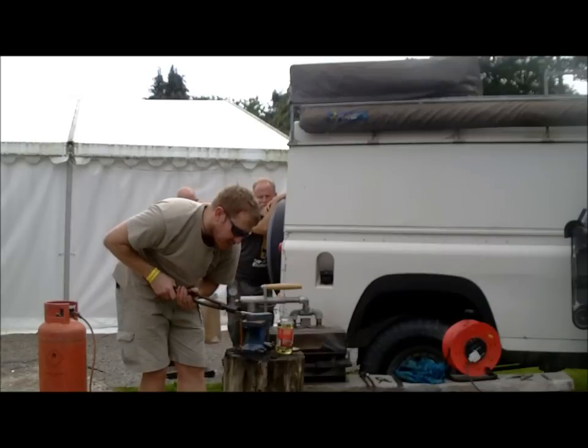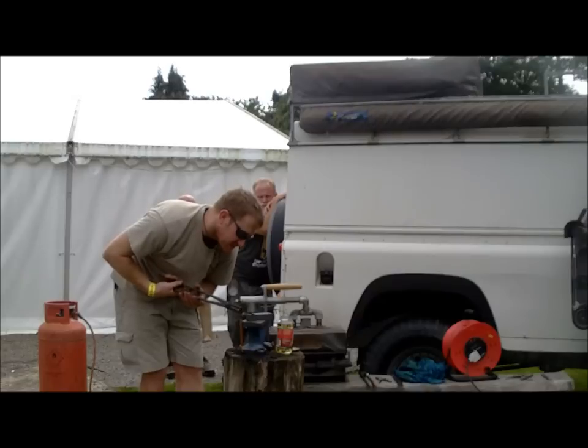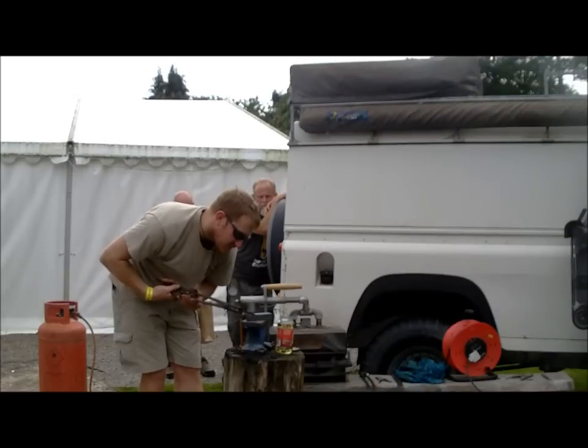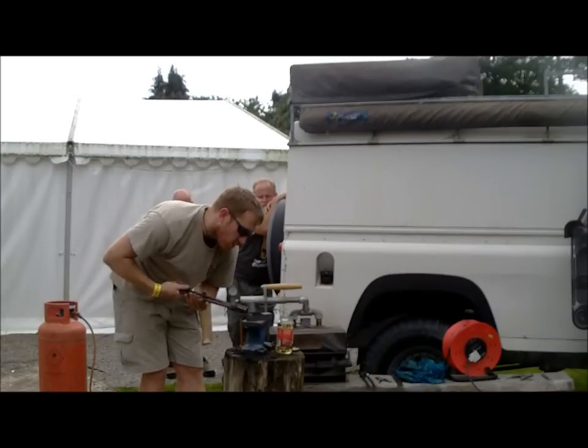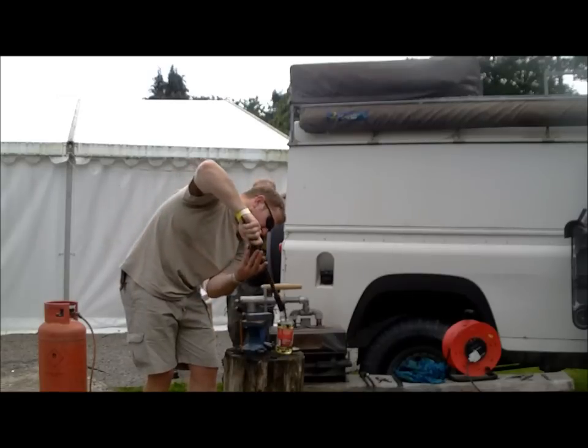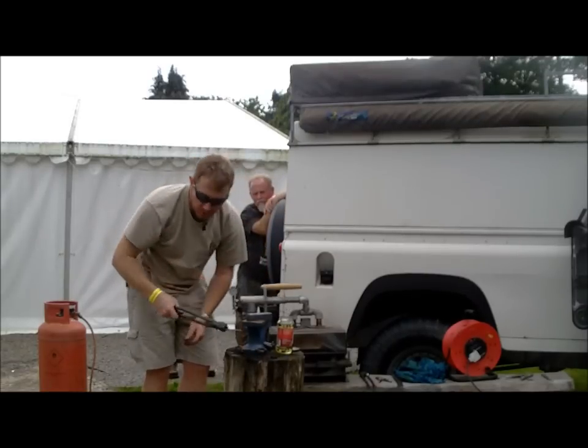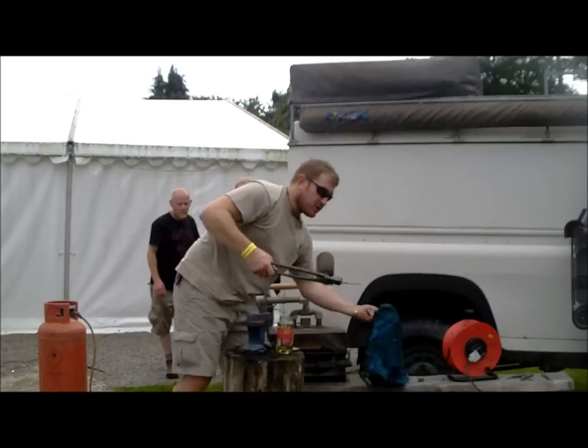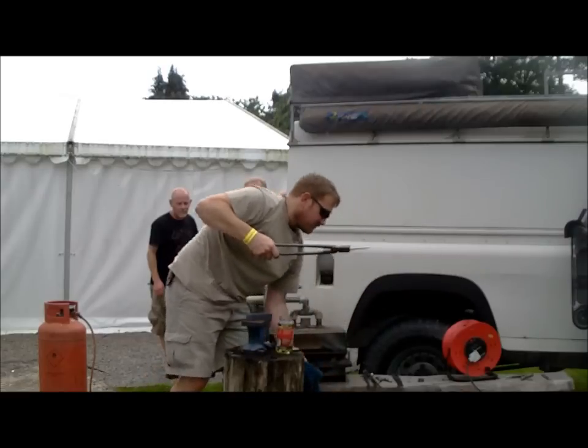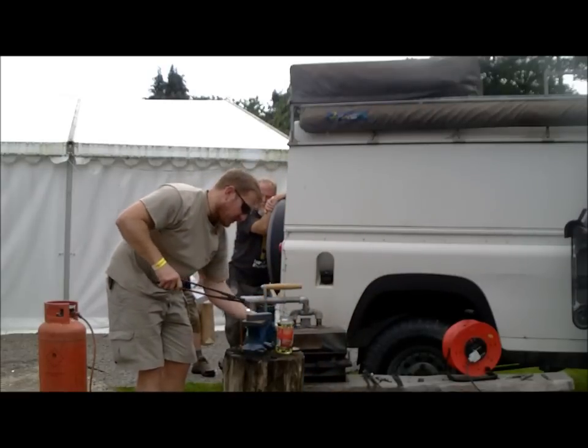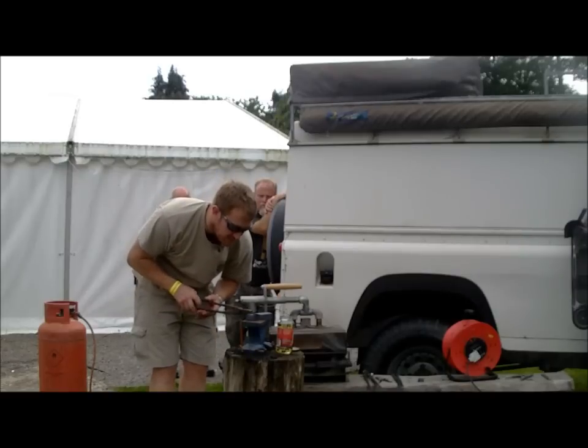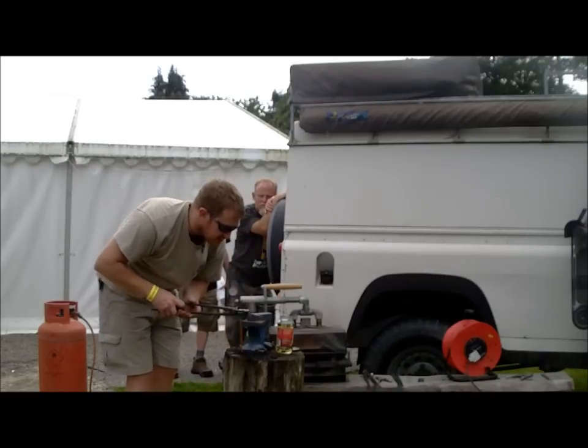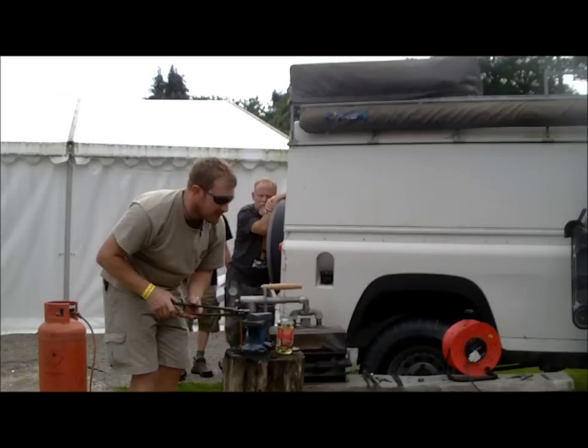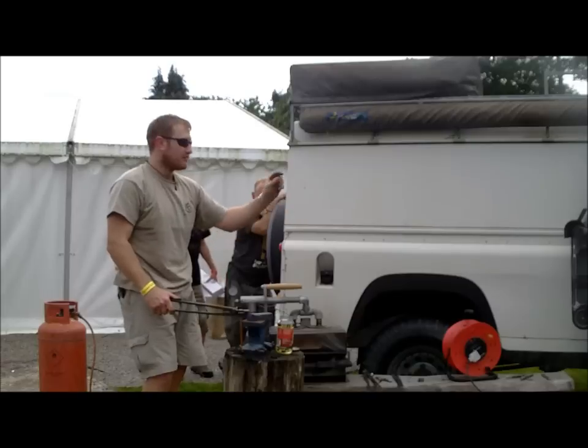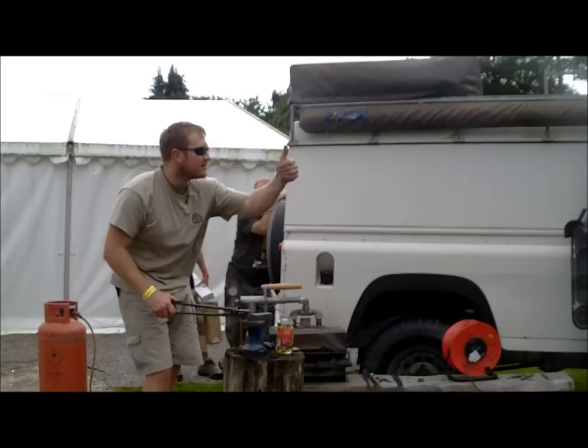Like I say, I'm being a bit tentative with the tip because I don't want it to get too hot too soon. And you can imagine the longer the blade, the more difficult it is to get it all the same colour. With a short blade, it's not too bad. But if you're working on something like Dave works on, a big 10-inch Bowie knife or whatever, you're going to have a lot more trouble doing it this way. That's why it's better to do it in an oven. You get a much more thorough job of it, and you're not doing it by eye, you're doing it by a set temperature. Hey, Barry, you alright?